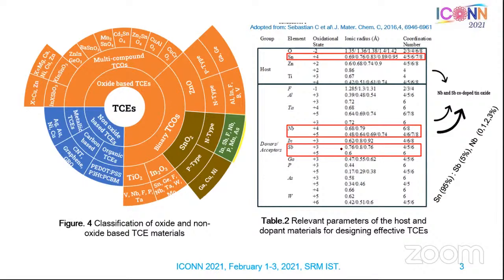But the main problem with antimony doped tin oxide is the gray color. It shows a gray color. So to decrease the gray color, we want to increase the transparency. For that, we want to dope with other materials which are suitable for the tin lattice. So we selected niobium as a dopant because its ionic radius is similar to tin. It also has a 5+ charge state, so it will donate 4 electrons to the host lattice and one more electron is used to increase the conductivity.